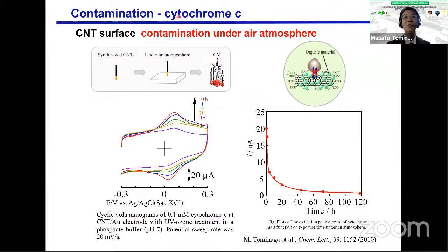Cytochrome C is a biomolecule, a redox protein. We observed a very nice redox wave of cytochrome C when we use fresh carbon nanotubes. However, when the electrode is exposed to the atmosphere, this peak decreased quickly. This is the peak current versus exposure time. The peak current decreases very quickly because this molecule is very sensitive to the surface.